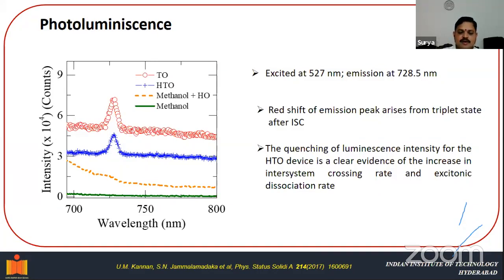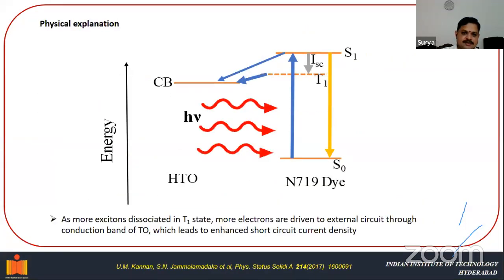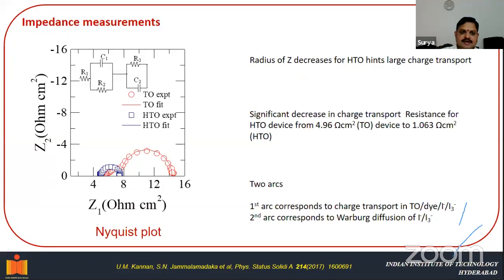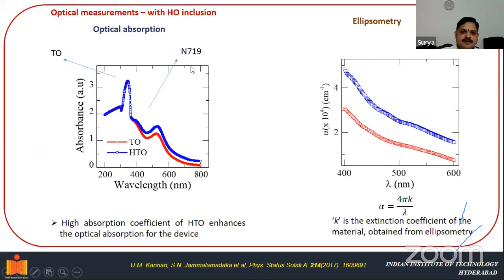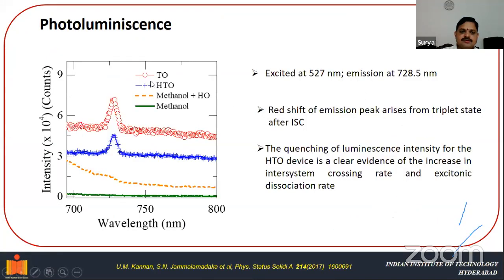The reason we have performed all these experiments is to support the JV characteristics of our device. We performed JV characteristics on the solar cell device, and we performed impedance spectroscopy to support our results. We also did the absorption spectra, ellipsometry absorption measurements, and the photoluminescence measurements. All these experiments supported our results, in the sense that as soon as we added holmium to the device, due to the strong spin orbit coupling, the efficiency of the device was enhanced.